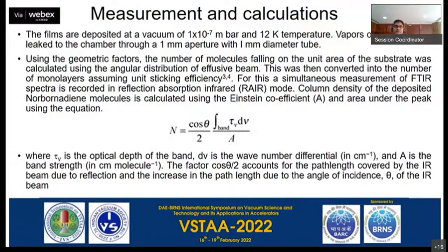Next slide, please. For that, we have devised a very easy and simple method from the deposited film by taking the Fourier transform IR spectrum of the deposited film. This is calibrated using an effusive beam deposition method, and from its geometrical factors, for example, 1 mm diameter and 1 mm aperture deposited at 10⁻⁷ millibar and 12 Kelvin, we have calculated the thickness assuming unit sticking efficiency, and simultaneously we have deposited and took the IR spectrum and from the column density, and using reflection absorption infrared spectrum method, we have calculated the column density using the equation n is equal to cos theta by 2, that is because of the reflection and absorption, and integration of the spectral band divided by the Einstein coefficient, absorption coefficient.